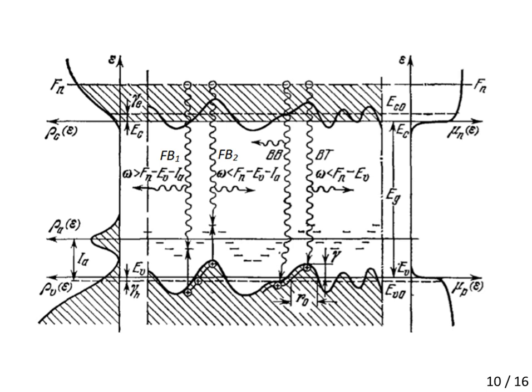Band-to-tail transitions are the recombination of holes localized at acceptor-like states of the valence band's tail with free electrons from the conduction band. And free-to-bound transition is the recombination of free electrons with holes localized at acceptors which are deeper than the mean energy depth of potential fluctuations. The energy levels of these acceptors are affected by the valence band tails. The characteristic feature of such bands is a broad and asymmetrical shape and a blue energy shift with rising excitation intensity.